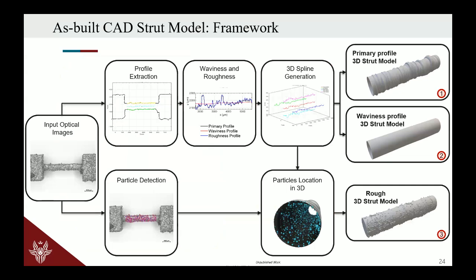And the simplified model is a kind of synthetic model, which substitutes completely the CAD strut model. So we want to create a kind of artificial substituting model that is able to completely remove the necessity of a CT scan analysis of your specimen. And so we propose a CAD strut model framework that is based on profile extraction, waviness and roughness, and 3D spline generation, that can be done without making any CT scan, which is very expensive and very time consuming.